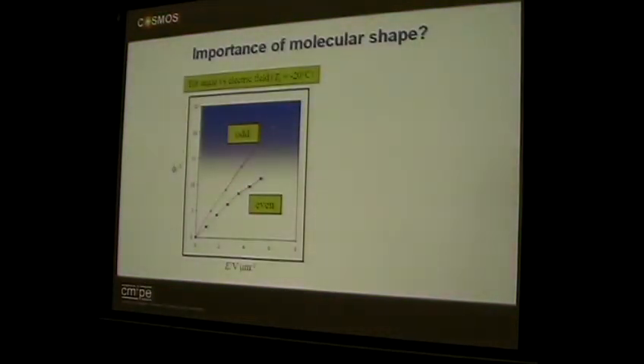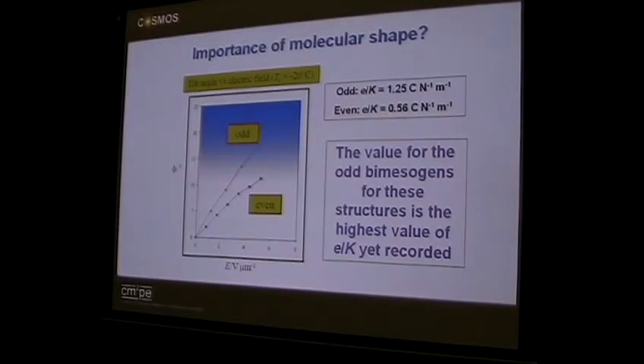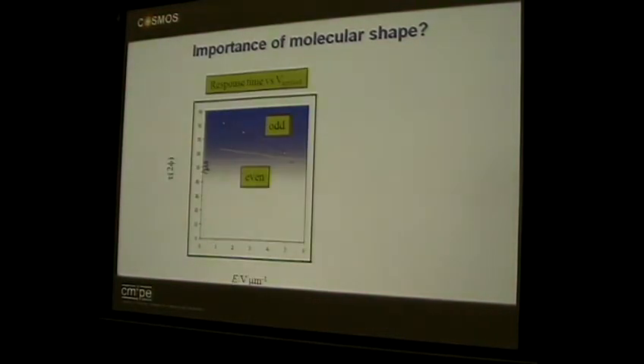If you look at the odd and even members of the series, just by changing one CH2, so adding one methylene spacer, you go from an E over K of nearly twice. So you're doing molecular engineering now. You're just changing structures slightly, changing what molecules do and how their shapes behave to generate high flexoelectric coefficients.